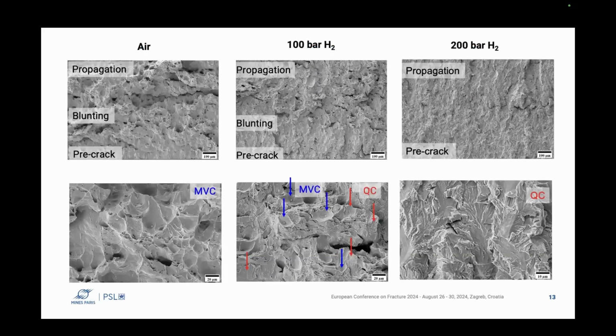Again, we see the fracture of these specimens. We can see the typical ductile behavior. We can distinguish between the pre-crack, the blunting, and the propagation. At the beginning of propagation, we have only microvoid coalescence. At 100 bar, we can still see the pre-crack, the blunting, and the propagation. But at the beginning of the propagation, we have a mixed aspect where we can see the coexistence of microvoid coalescence and quasi cleavage that affects the toughness.